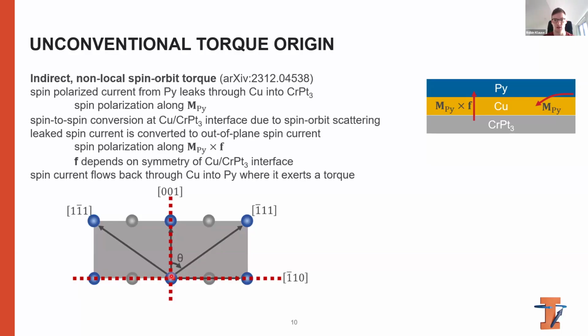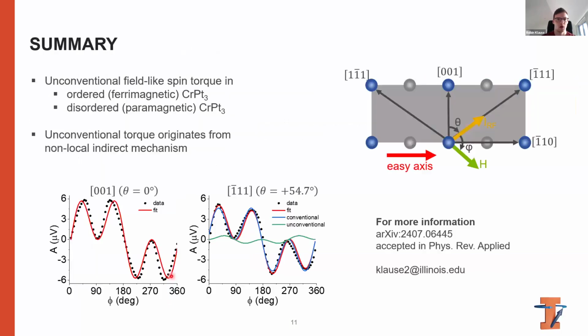So this is what explains how we can get unconventional torques in both ordered and disordered samples without the role of magnetism involved. To summarize, we measured unconventional field-like spin torques in both ordered, which is ferromagnetic chromium platinum 3, and disordered, which is paramagnetic chromium platinum 3. We attribute these unconventional torques to the non-local indirect mechanism I just mentioned.